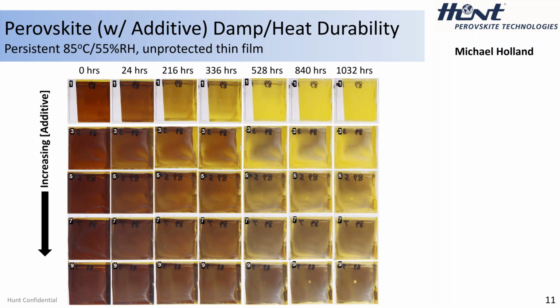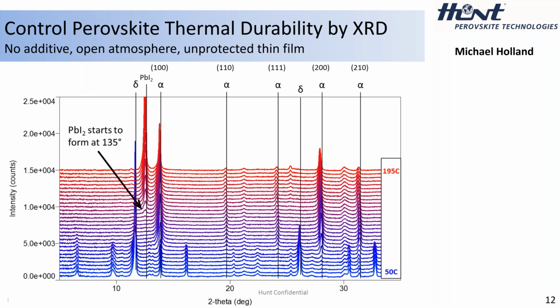Further, we have a nice little Anton Paar setup that I'll talk about in a minute for our thin film XRD, and it allows us to load materials in and control the atmosphere and the temperature of the stage. And you can see in this case, that same material without the additive, we put it into the Anton Paar, we can get up to about 135 Celsius, and it starts to decompose a little bit. You start to get a little lead iodide peak, denoted there at about 13 degrees two theta in the diffraction pattern.